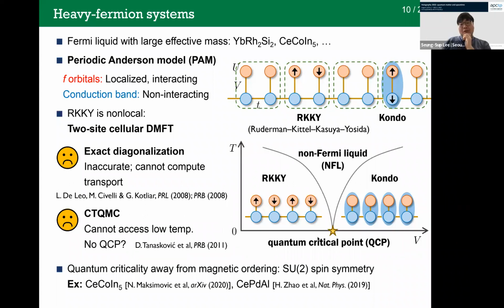To focus on the nature of this quantum criticality in heavy fermion systems, we enforced the SU(2) spin symmetry of the system. So there is no symmetry breaking. This RKKY phase has strong antiferromagnetic correlation as in quantum magnets, but actually there is no Néel ordering, so the symmetries are not broken. It is not a mere theoretical setup. Indeed, there are real materials whose quantum critical points are separated from the magnetic ordering.